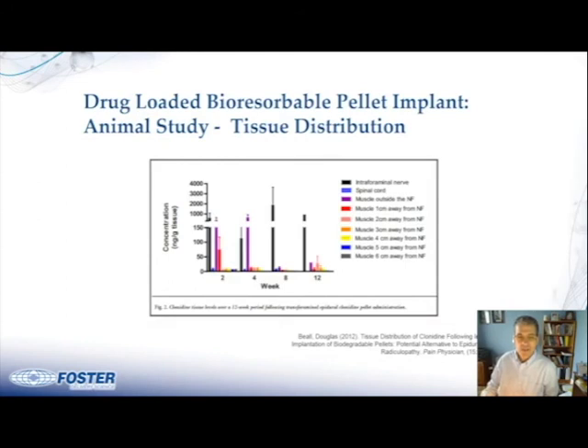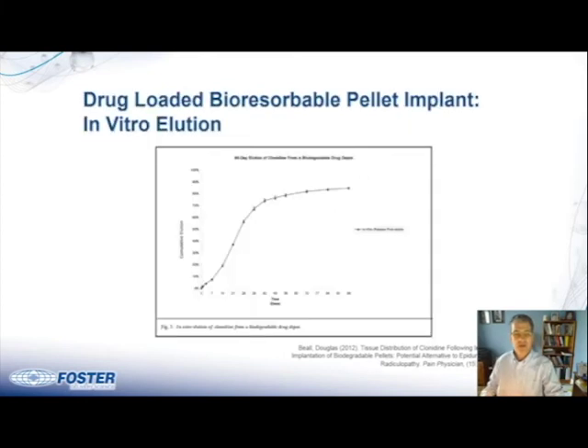Here you can see that the drug was detected closer to the implantation site within the first 2 weeks of implantation. And after 12 weeks, clonidine was detected as far as 4 centimeters from the implantation site. And here are the in vitro results where that shows the drug elution levels off at about 90% after 98 days. So it's a pretty long implantation period that's achievable with this implant.